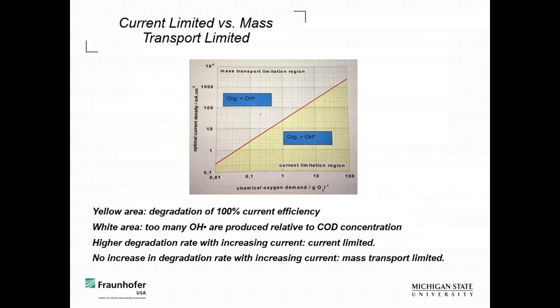This elaborates on this need to get things very close to the electrode surface. This is a model that was developed by, I'm forgetting his first name, his last name is Comninellis, but he's done a lot of theoretical work in wastewater treatment and electrochemical oxidation. Here you have COD, so this is basically the amount of oxidation that we need in order to reduce what sort of contaminant we have in solution. Then here's current density on the Y. And so you have this mass transport and current limited region. Unfortunately for PFAS, because the concentrations are so low, this is in grams per liter, so we are, what, 1 billion times lower than this? So we're almost always in the mass transport limited region. So we've had to do some innovative things with our reactor design to ensure that we're getting down to these low levels. And this is also why we're going after two specific niche applications that I'll talk about.